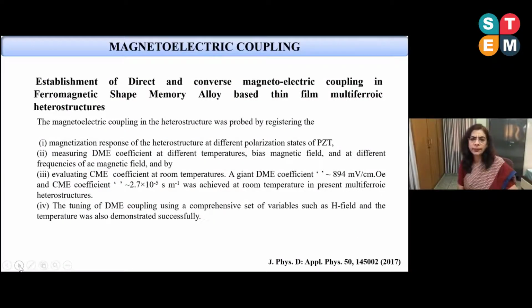So the very first work we did was the establishment of the direct and converse magnetoelectric coupling in these heterostructures. That was probed by registering the magnetization response of the heterostructure at different polarization states of PZT, then measuring the direct magnetoelectric coefficient at different temperatures, bias magnetic fields, and frequencies of AC magnetic field. We also evaluated the converse magnetoelectric coefficient at room temperature.